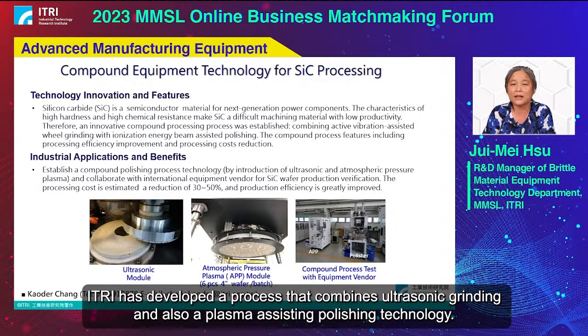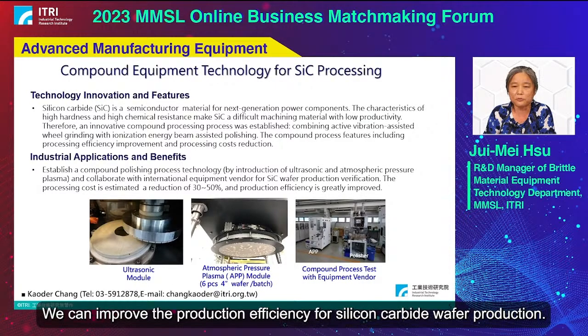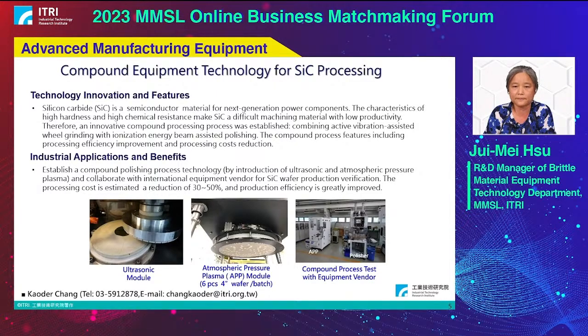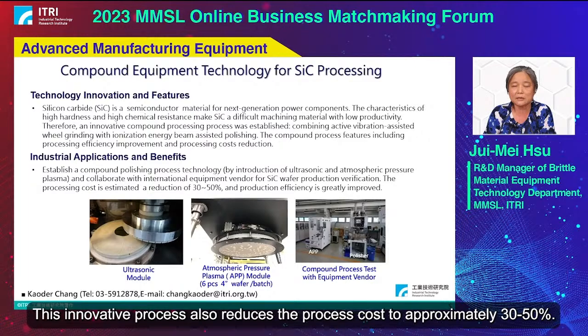ITRI has developed a process that combines ultrasonic grinding and also a plasma-assisted polishing technology. We can improve the production efficiency for silicon carbide wafer production. This innovative process also reduces the process cost to approximately 30 to 50%.